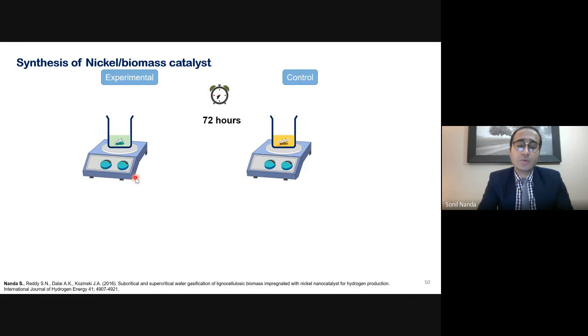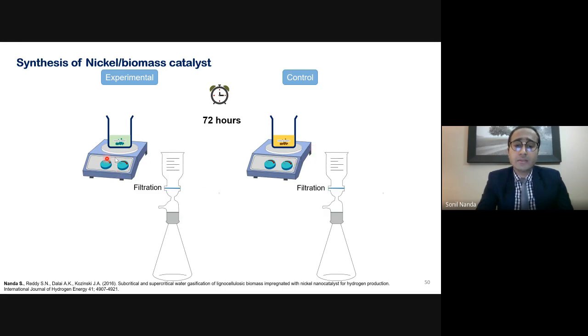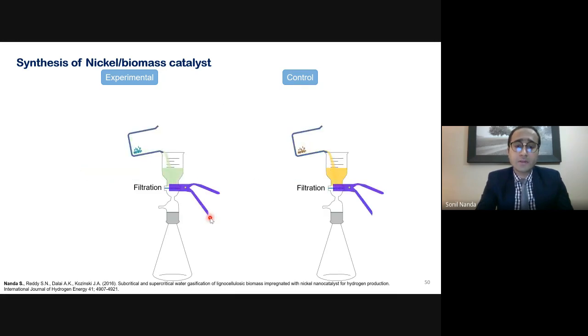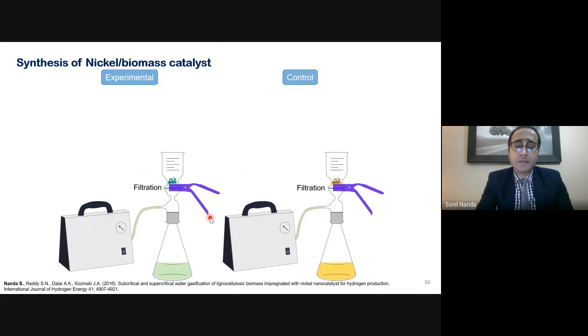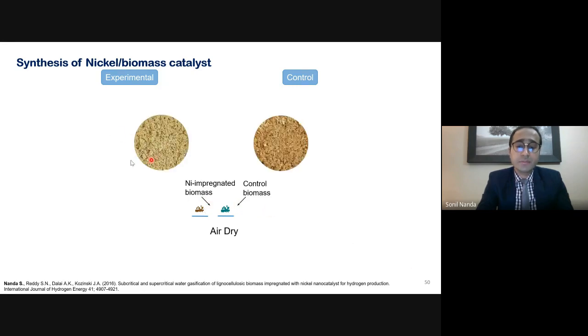For 72 hours, the solute and solution were mixed together so that the nickel present in the nickel nitrate solution will penetrate into the biomass cell wall and end up generating nano nickel particles. After that, the slurry was filtered, and then the biomass impregnated with nickel and the control biomass were air dried and further investigated for gasification experiments. So this is a nickel impregnated feedstock, and this is a control biomass.